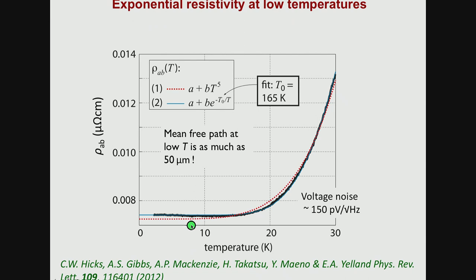And although the difference is small, if you're doing a low noise measurement, you can very clearly distinguish what the resistivity is really doing there from the red dotted line. The red dotted line is the T to the fifth that you would have in what's called the Bloch-Grüneisen law that many of you will have come across as undergraduates. Actually, the function that you're able to fit through the resistivity is exponential, and if you just do that blindly, you fit out a characteristic temperature for your exponential, meaning that you have some sort of gapped process of scattering. You get out a temperature T naught, which would be about 165 Kelvin.